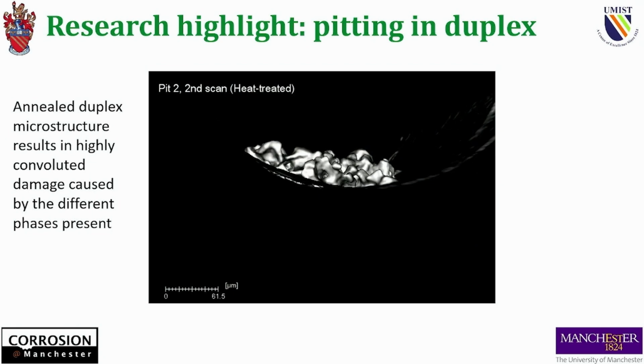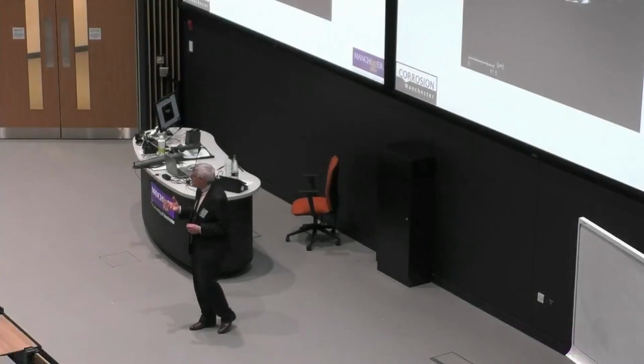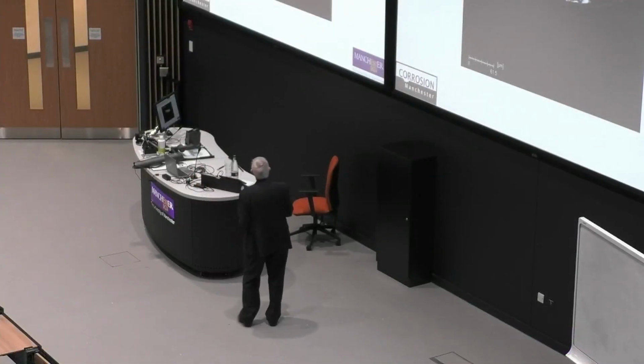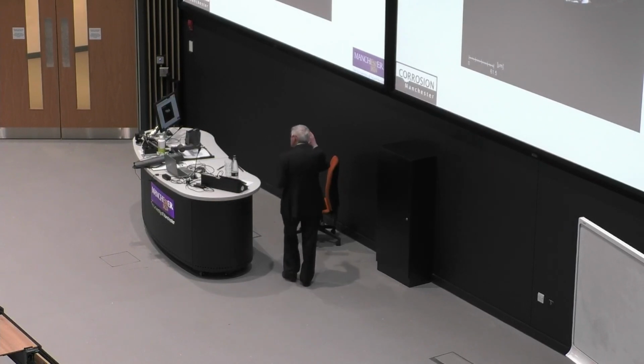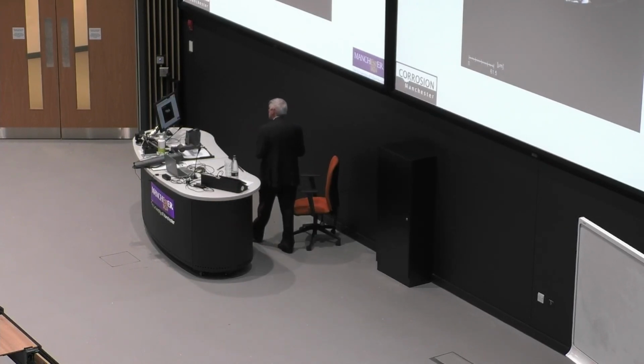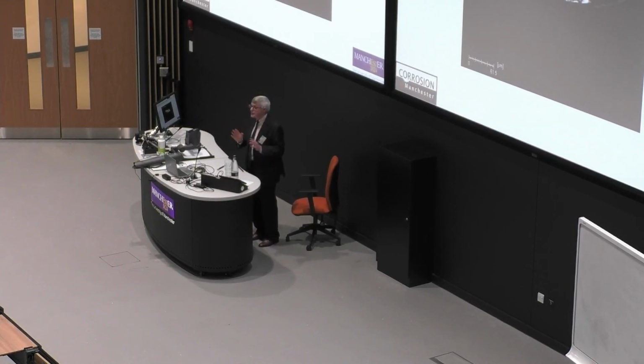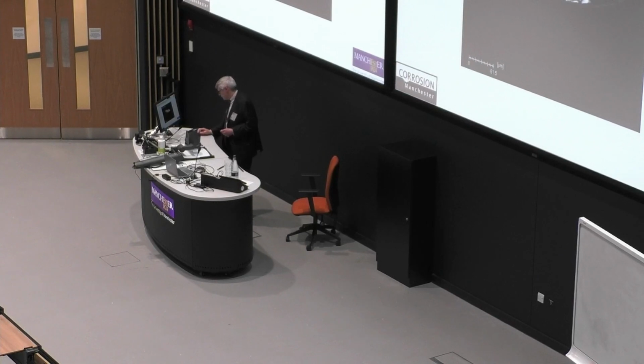Okay, so you can use that information to understand how the pitting process works in 3 dimensions, not just 2 dimensions. And I don't have space to do the annealed. This is the annealed duplex microstructure. The quenched duplex microstructure corrodes in a completely different way. A single hemispherical pit, essentially.